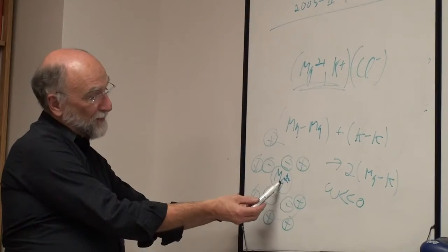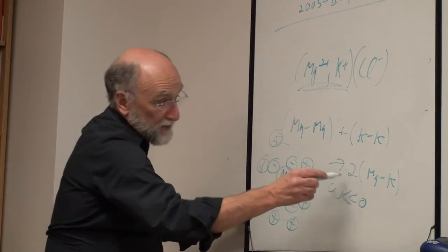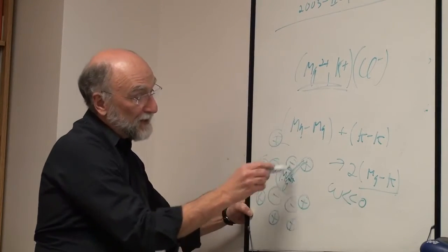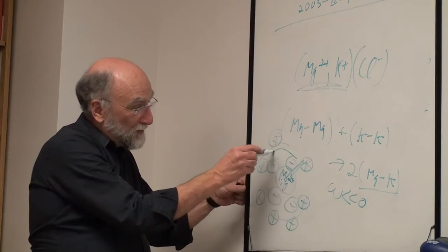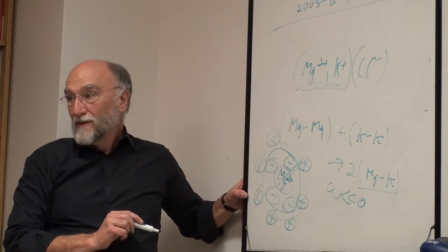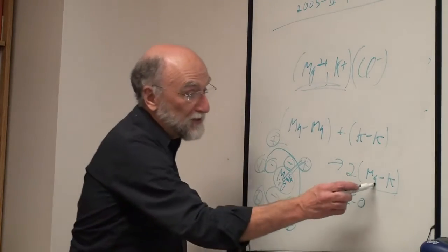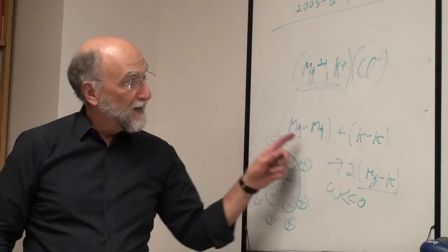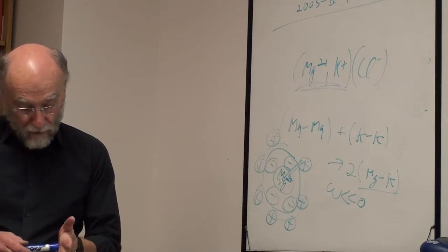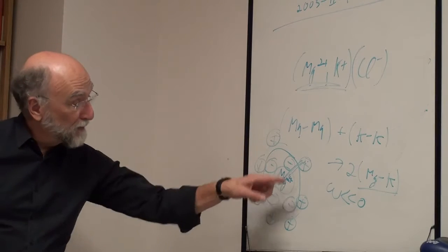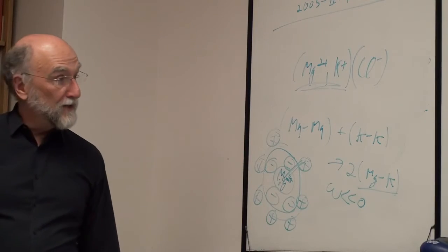So here's your magnesium, first coordination shell is chlorine, second coordination shell is potassium, which means that you favor magnesium-potassium second nearest neighbors. That is almost equivalent to talking about MgCl4 anion complexes. If you treat this system with a one-sublattice quasi-chemical model, you are not explicitly talking about complex ions, but you end up with something that's mathematically about the same thing.